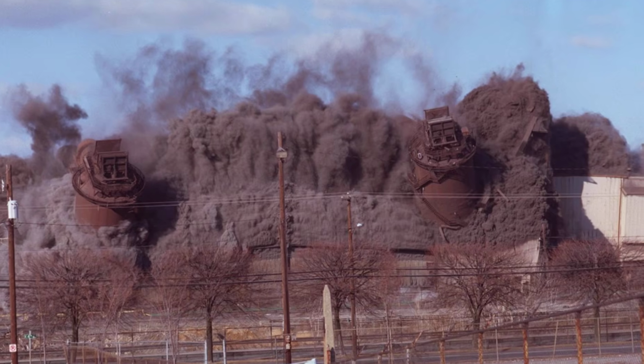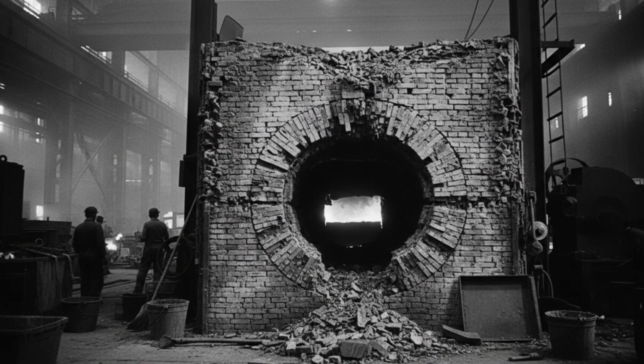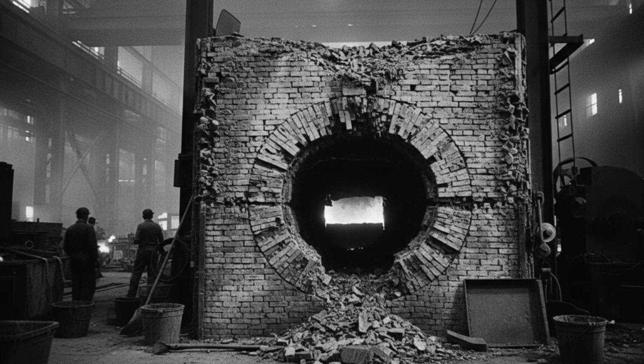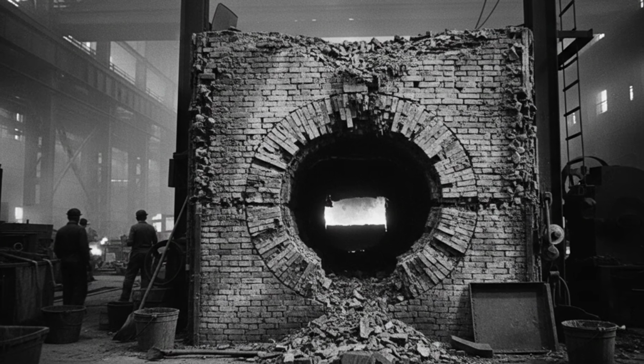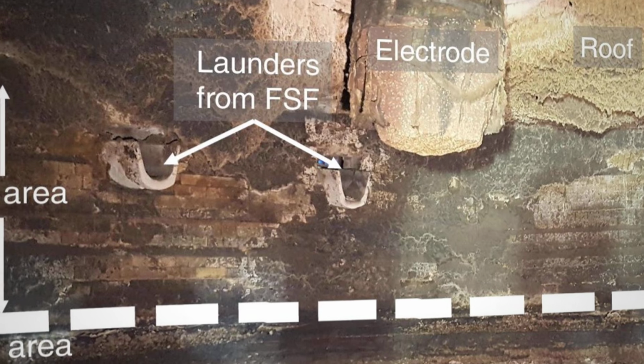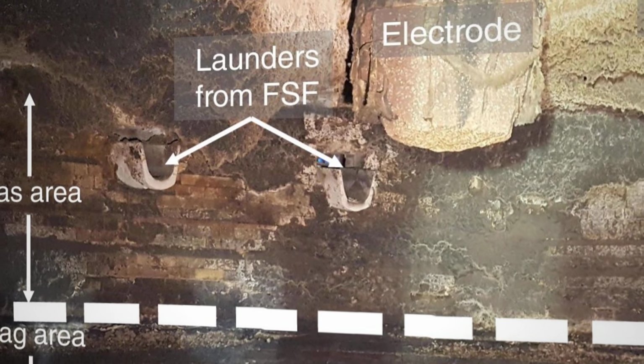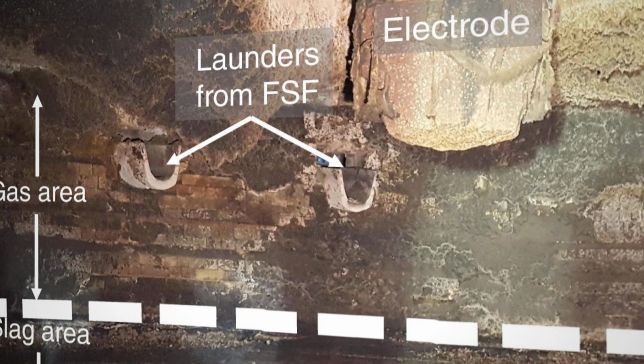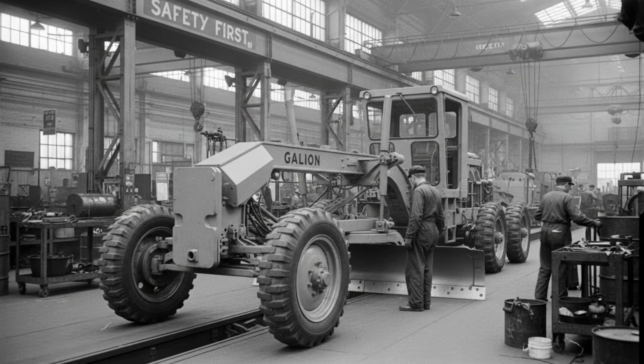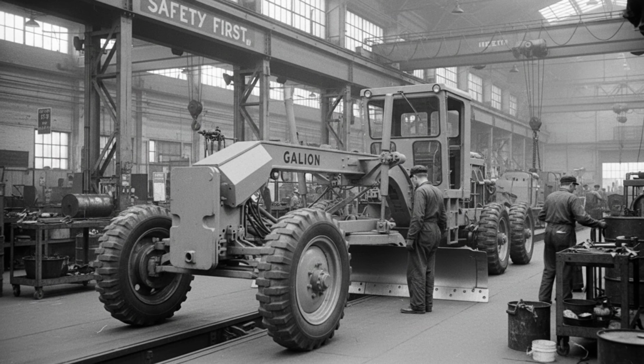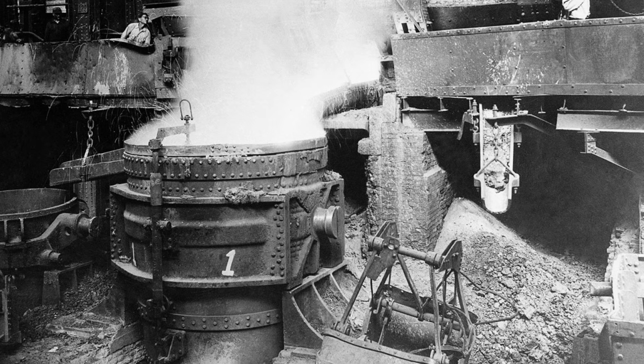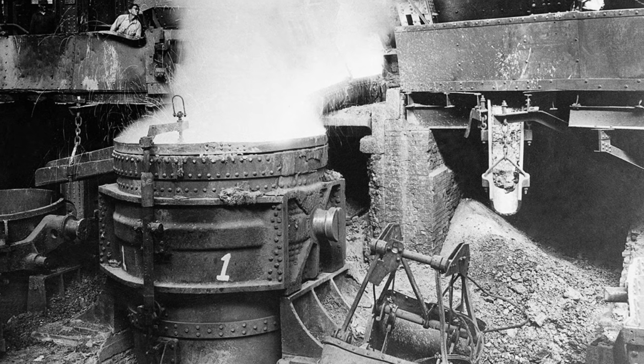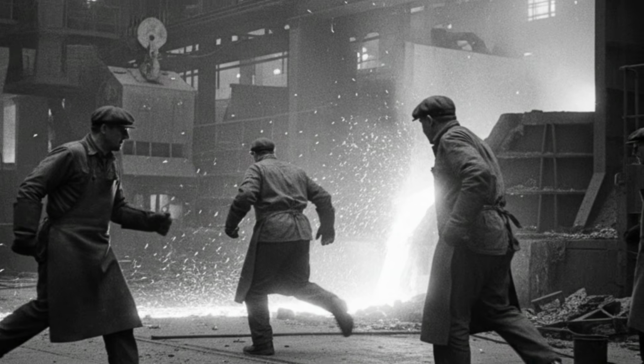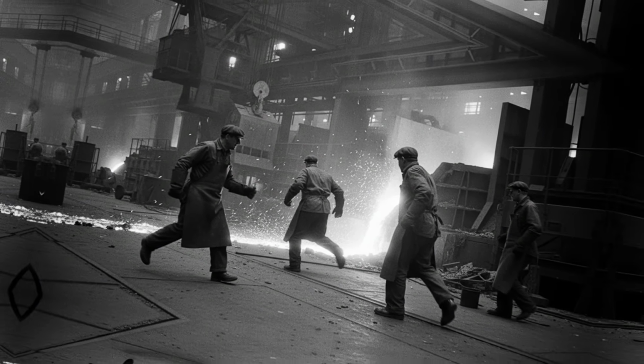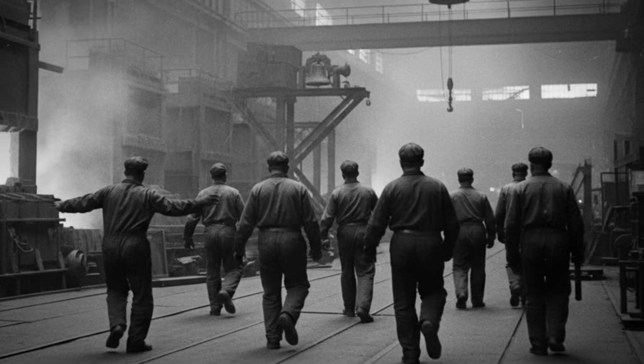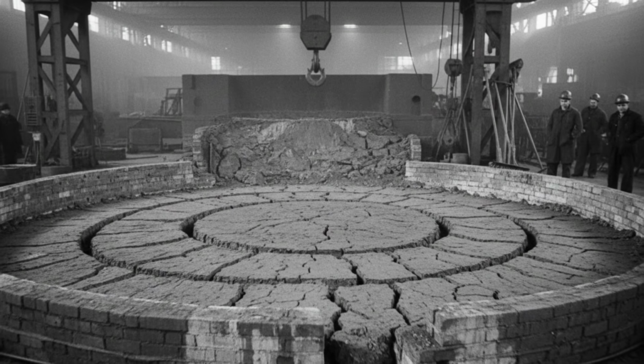The word for what happened at Bethlehem that day, and for the more random version of the same event that occurred when a furnace lining eroded too far between heats, was breakout. A furnace breakout meant the refractory wall had been pushed past its limit by heat or chemical erosion or physical stress, and the liquid steel found its own way out before anyone called a tap. It came through the wall, through the floor of the hearth, through wherever the lining was thinnest. It moved fast, spread fast, and the only response was to get everyone in the building away from it and wait for it to cool enough to be dealt with.